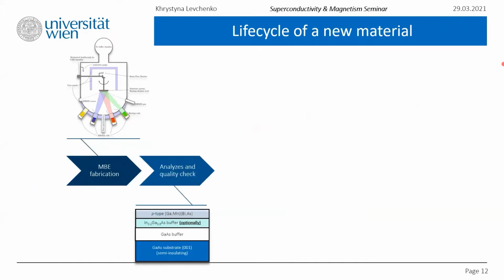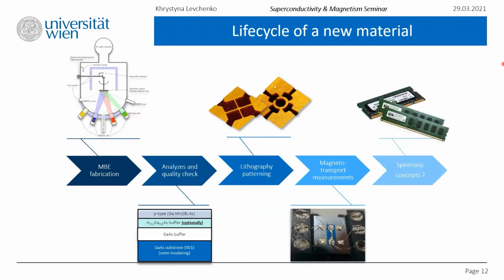And this is the life cycle of the dilute magnetic semiconductor sample. We start with the growing procedure, again low temperature molecular beam epitaxy. Then, after obtaining samples and going through some post-growth treatment, being annealing, we proceed to analyzing whether we have good samples. So structural analyses are important at this stage. The best samples are then chosen, and on them we perform some lithography patterning if we want to do one.